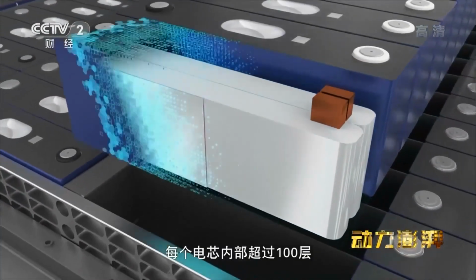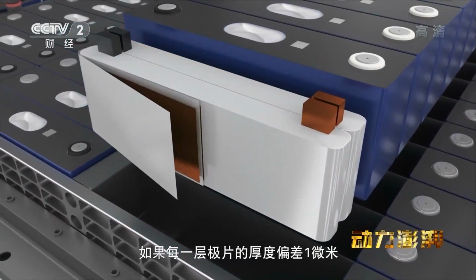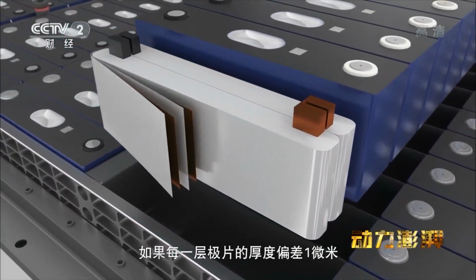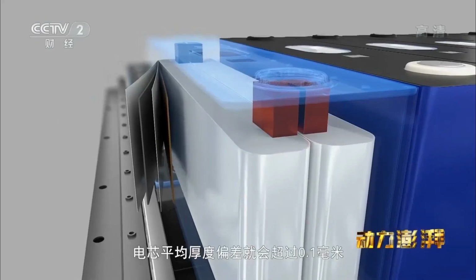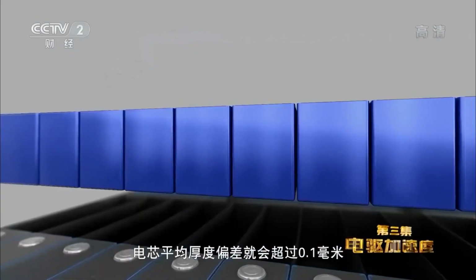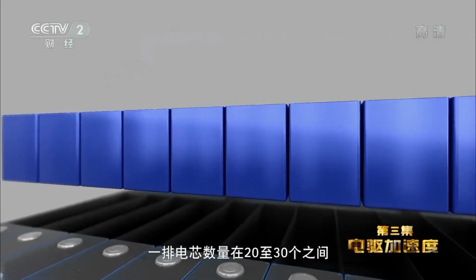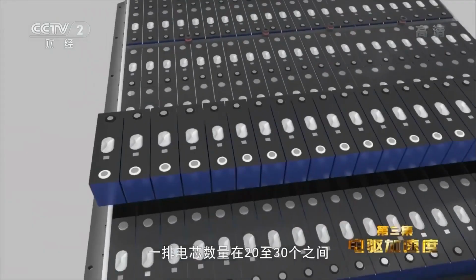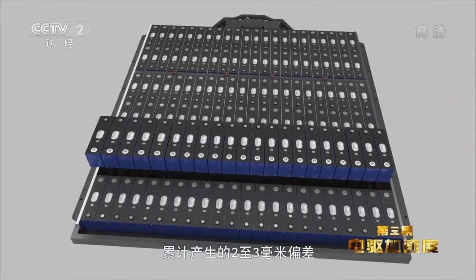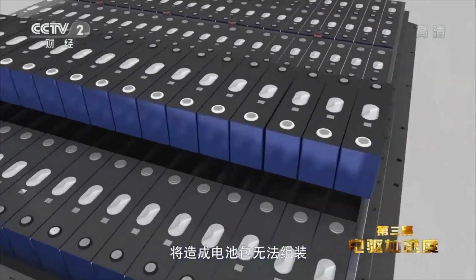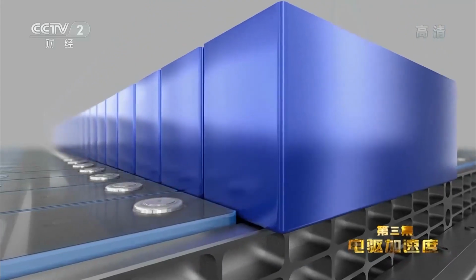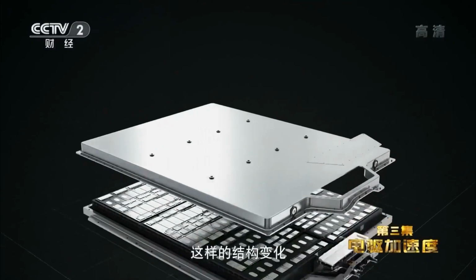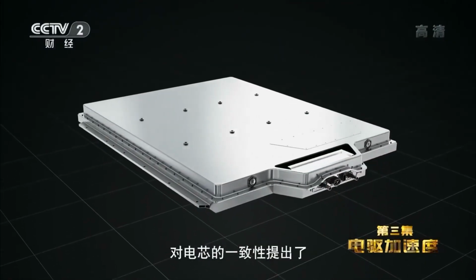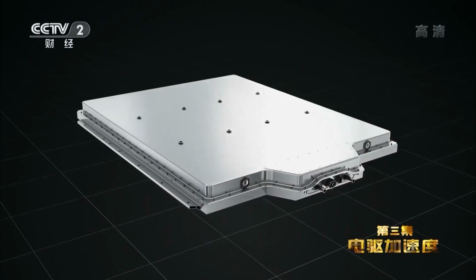However, there are more than 100 layers inside each cell. If the thickness deviation of each layer is 1 micron, the average thickness deviation of the cell will exceed 0.1 millimeters. If the number of cells in a row is between 20 and 30, there will be a cumulative deviation of 2 to 3 millimeters. This will prevent the battery pack from being assembled. Such structural changes impose an extremely high requirement on the consistency of the cells.